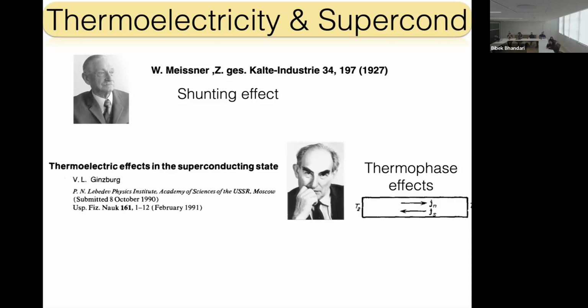And Ginzburg wrote this wonderful paper in the 40s, essentially, where he predicted the thermophase effect. Essentially, he said, okay, even in a superconductor, you have quasi-particle states. Quasi-particle states behave similarly to simple electron states in a metal. So essentially, for those states, you can get thermoelectricity and you can get a current. And then the system reacts, generating a sort of Josephson current that goes in the opposite direction to compensate. And so in the end, the gradient of temperature will determine a difference of phase. This is called the thermophase effect, and it was even measured, okay? Essentially, in the 70s, they started to measure it, there were some problems. Everything was fixed at the beginning of the new millennium.